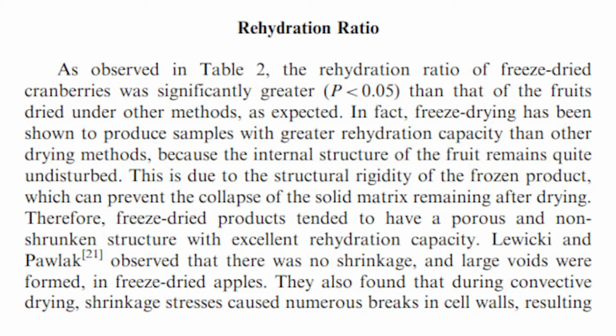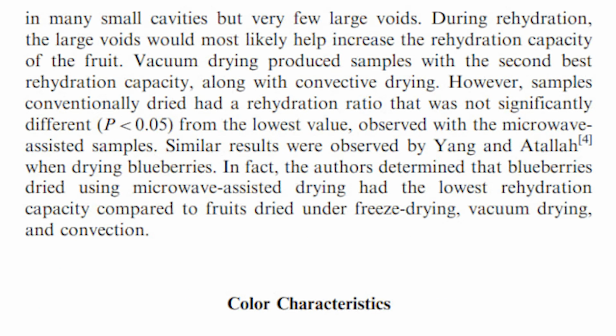They also found that during convective drying, shrinkage stresses caused numerous breaks in cell walls, resulting in many small cavities but very few large voids. During rehydration, the large voids would most likely help increase the rehydration capacity of the fruits. Vacuum drying produced samples with the second best rehydration capacity, along with convective drying.